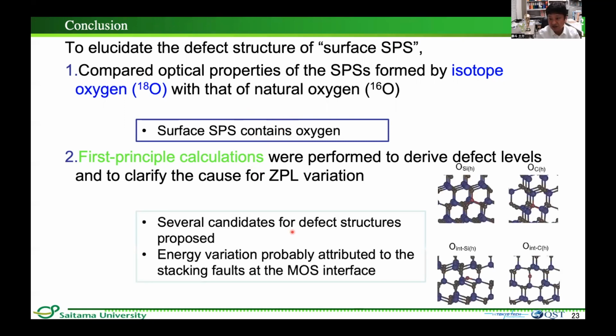From the calculations, several candidates for defect structure were proposed. Furthermore, the cause for energy variation was clarified, which is probably attributed to the stacking faults at the MOS interface.